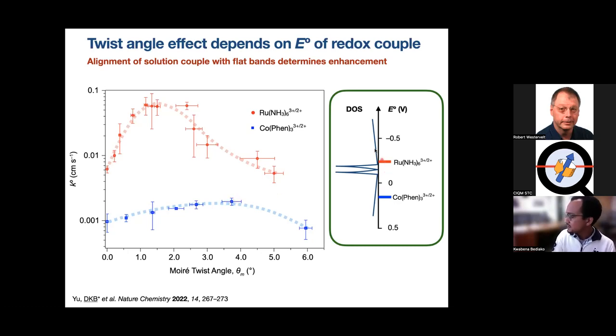And the reason for that, it turns out, points to the importance of the flat bands of the twisted bilayer graphene and the density of states enhancement being well aligned with the particular formal potential of the molecule that you're trying to oxidize or reduce. So in the case of our ruthenium molecule in red, we have pretty good alignment with where we expect these flat bands to be. So we do see an enhancement or an effect of twist. Whereas with our cobalt molecule, by the time we apply enough potential to drive this reaction, we've already moved our Fermi level far enough away from where these flat bands are, broadened as they might be at room temperature, that we basically see no enhancement.